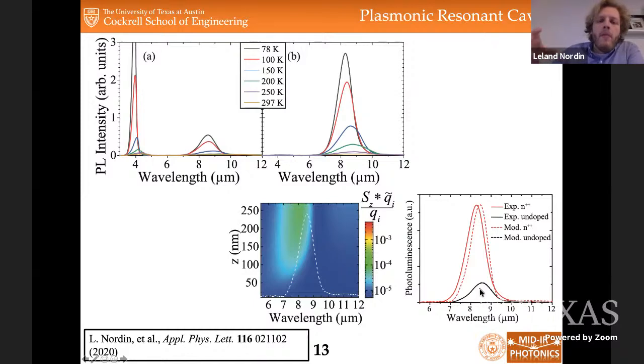And this theory associated with why we see the emission enhancement that we do, we worked on with our collaborators at UMass Lowell, Professor Viktor Podolskiy's group, and it's a product of the Z component of the Poynting flux, which is S sub Z, and then also the Q tilde, which is your Purcell enhancement, so this additional photonic density of states. Essentially, though, we were able to accurately model this photoluminescence enhancement. It's about a factor of 6.